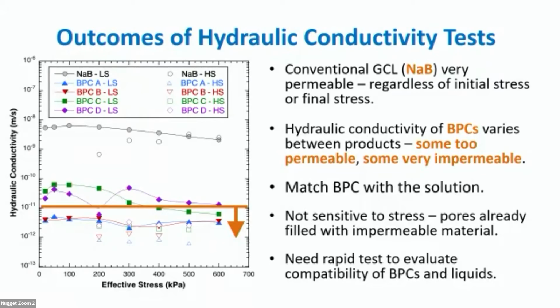And when we ran the tests with the high stress tests, all of them were below. And in fact, with the high stress test, we always got lower hydraulic conductivities, largely because we had compressed that system before it had ever been contacted with the heap leach solution.